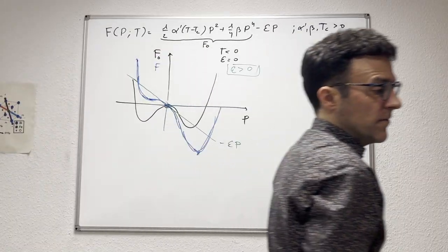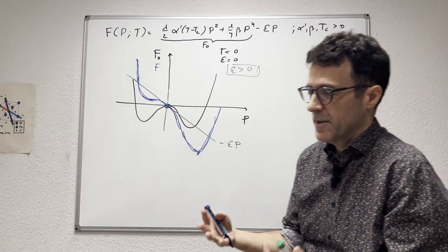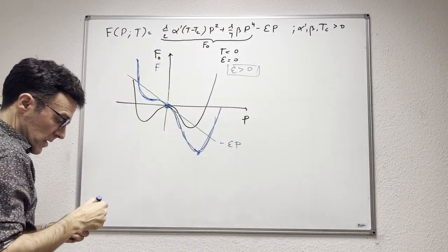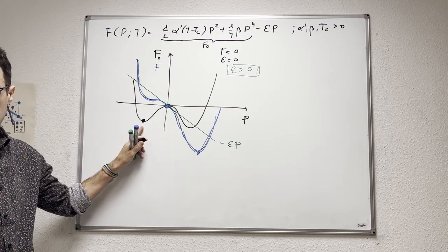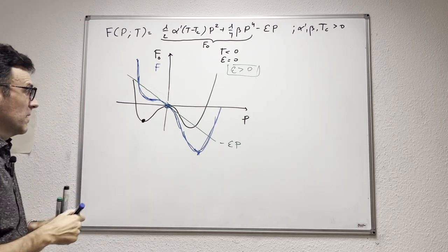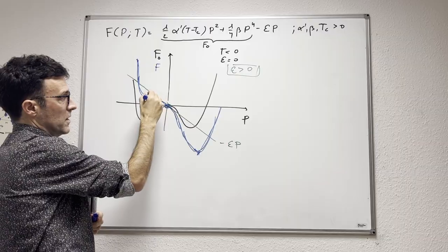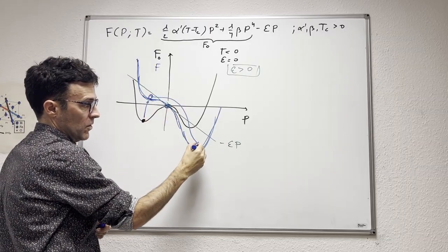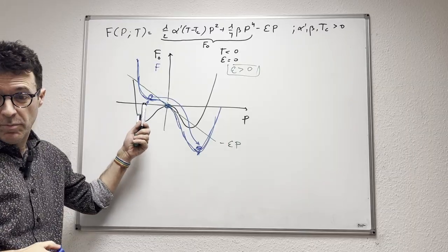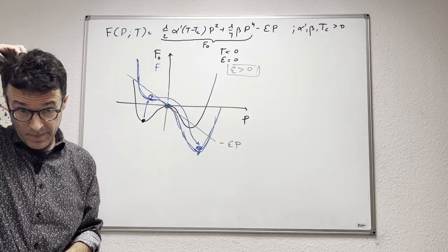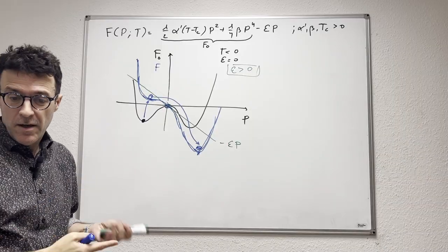So then the basic thing that an electric field does is quite obvious, and it is also obvious that this simple theory may allow us to describe phase transitions, right? Not phase transition, sorry, switching. Why? Because if I start here at 0 field, imagine I start in a negative polarization state. When I put the field, essentially what I'm going to do is to penalize the energy of this state, so the energy goes up, and eventually this state will come all the way here. Not this state, the system. The system will change the state from a negatively polarized one to a positively polarized one.